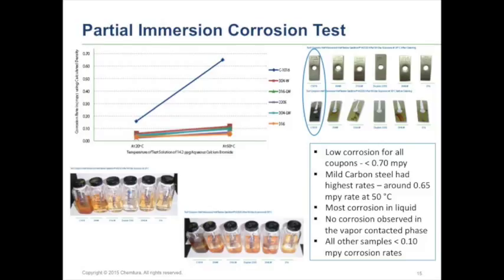Now, on the partial corrosion, I will say these solutions look a lot like what the liquid tests looked like as well, so this was not a surprise. Very interesting, with half the coupon in the liquid and half in the vapor, you also ended up with about half the corrosion rate. So basically what you would expect. There was no major impact at the interface, and for the most part the corrosion rates are still fairly low, less than 1 mil per year. You can see there was some pitting and some evidence on the surfaces, but for the most part, the duplex and the stainless steel all performed very well, and even the carbon, given the application, did fairly well.